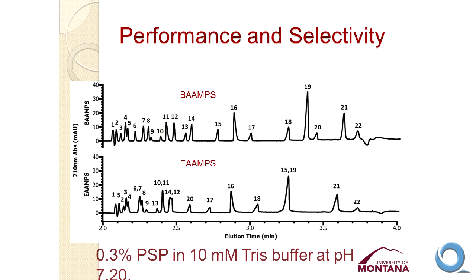If we carry this research on and we look at butyl acrylate AMPS copolymers versus ethyl acrylate AMPS copolymers, this is a separation that was achieved by Jesse Hislop, my student, who took 22 different substituted benzene and naphthalene compounds and separated them in less than 4 minutes using each of these two different nanoparticles as the pseudostationary phase. In general, we see very high efficiency. We do see a little bit of tailing sometimes, a little bit of fronting sometimes.